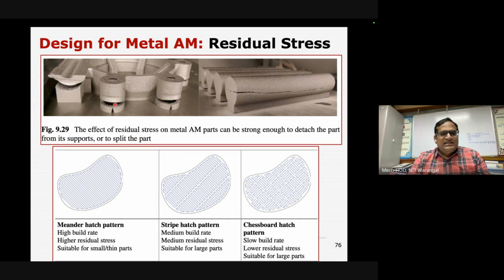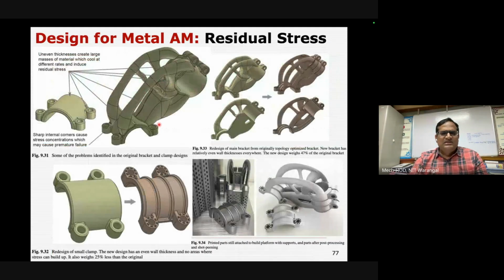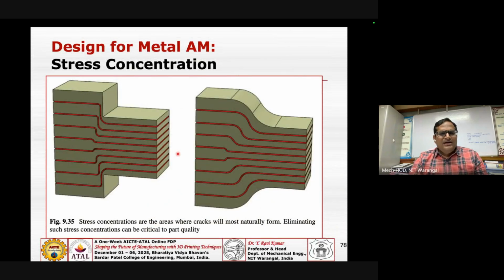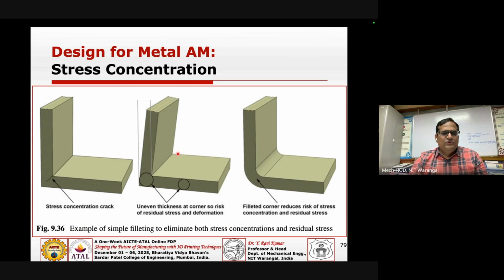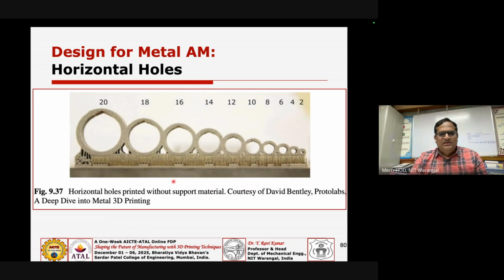And residual stresses, as I already mentioned, may detach the support from the model, and also cause a lot of internal cracks. One way of doing it is to change the scan patterns, optimizing these patterns in order to reduce the residual stresses. And also thickness is another area where you try to maintain uniform thickness across the entire structure rather than abrupt changes in thickness. And of course, stress concentration and uniform thickness across the walls.